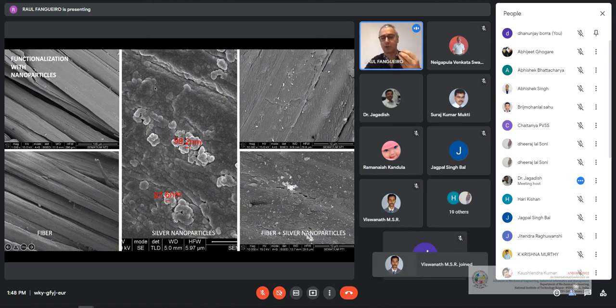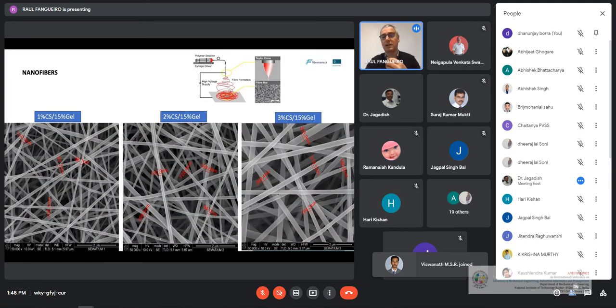But we can do more. We can have the fibers and functionalize them, or we can use techniques like electrospinning, which gives us the possibility to produce nanofibers, fibers at nanoscale, and at the same time, when producing these fibers, to functionalize them with nanoparticles again. And you can see here several mats of fibers with different diameters, functionalized in some way with other nanoparticles, with graphene, for instance, and I will show some examples about that.